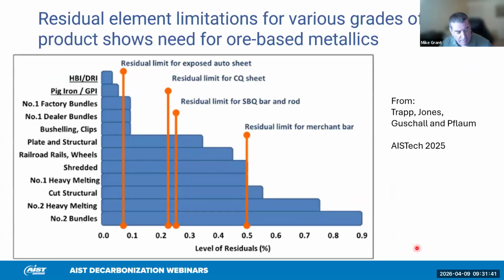Now, why do we use DRI? People will say, well, scrap and 100% hydrogen-based DRI are similar. We all know that scrap contains impurities, which we call residuals. And the amount of residuals present in the scrap, if that melts into the steel, can limit the kind of steel that's being made. So, for example, for producing high-quality exposed auto sheet, the limitations for the amount of residuals that you can melt in is quite low. And therefore, given the types of scrap that's available on the market, quite often you have to dilute this scrap with ore-based metallics such as DRI or pig iron. And in fact, this is absolutely necessary when making exposed auto sheet.